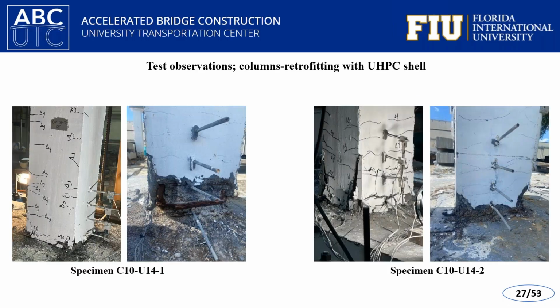This figure shows the failure mode of both retrofitted specimen using UHPC jacket. As can be seen, fracture cracks in both specimens developed within the height, but compared to the previous specimen, plasticity occurred over a shorter length. This demonstrates actually a higher stress concentration in the specimen C10 U14-1, similar to a specimen with normal strength jacket. Failure occurred when the crushing of the concrete penetrated through the jacket, causing the longitudinal rebar to lose the UHPC as a lateral strength and subsequently buckled.